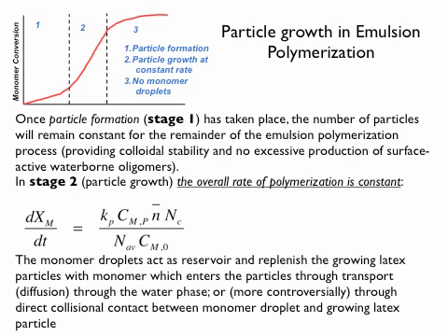If coagulation events happen, the number of particles drops. And if nucleation continues to happen, for example if you have a very large radical flux, so a lot of oligomeric species are formed that are derived from a sulfate radical, you could trigger an extra nucleation event.